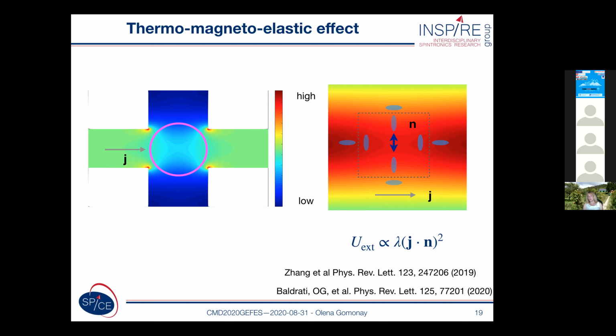So you see that within the dashed square in the right panel, all the ellipses are oriented in the same direction. And this means that the average strain will favor orientation of the Néel vector, which is perpendicular to the orientation of the current. This effect of thermomagnetoelastic coupling can be phenomenologically described with the energy expression as shown below the figure. So the contribution to the anisotropic energy of the system is proportional to the square of the cosine between the current and the Néel vector.